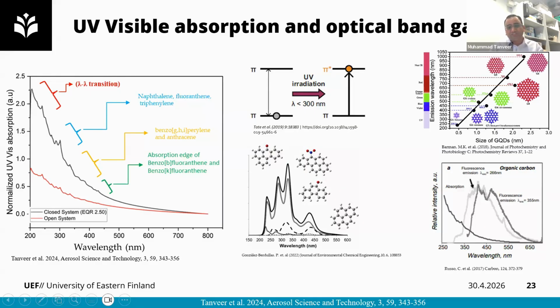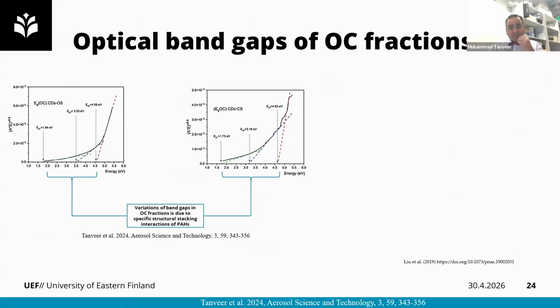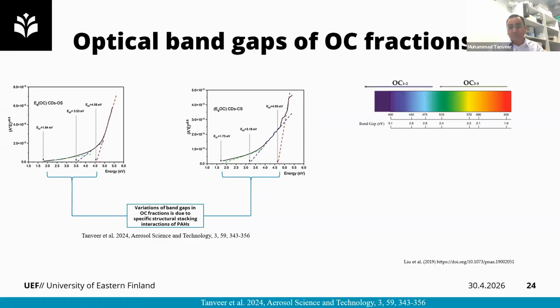It is considered that the size of carbon dots is the major key factor in controlling the optical features. But here we have seen that composition and functional groups on the surface of carbon dots are also very important in defining the optical features of the nanostructures. As far as the optical band gap is concerned, the OC fractions exhibit different band gaps, because these nanostructures are composed of different fractions of OCs. Depending upon the nature of the OC fraction, they will absorb different light and exhibit different band gaps. The variation of band gap is basically due to the specific structural stacking interactions of these polyaromatic hydrocarbons. So you can see here how the band gap is changing according to the OC ratios.